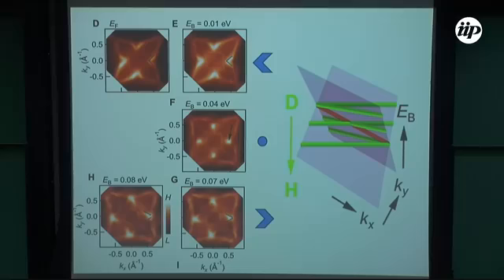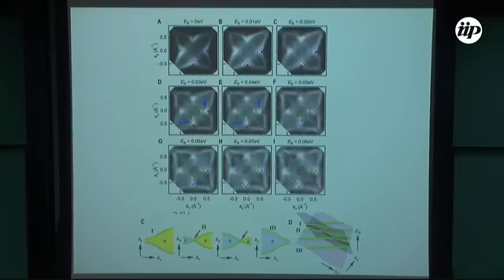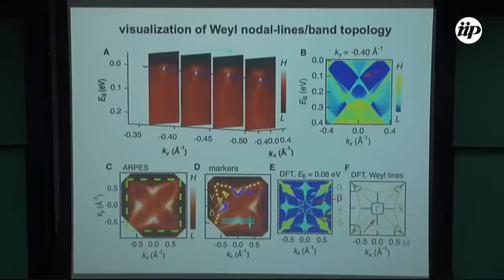So we want to see in these materials, what is the band topology? Is there a Weyl node hidden in the band structure? So we see that there is a crossing. In other words, there's a zero mass object in 3D. So it's a Weyl node in 3D. This material has many bands. We do that on all these bands that this material has, and we explore all these details. Where are the Weyl points, where are the loops, and where are the surface states? So this is one example of that.